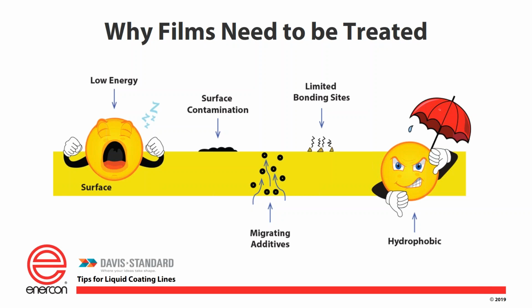So the number one reason why we're treating these films anyway is you guys have lazy film. The films you have are all low energy. So when you buy a polypropylene or a polyester or a polyethylene film, and you're trying to convert it, like in Lee's case, we're trying to get a silicone coating to wet that surface. In and of itself, that pre-treated material, as Lee identified in an earlier slide, relative to these starting dyne levels, is just not adequate to allow that silicone coating, for example, to wet the surface.